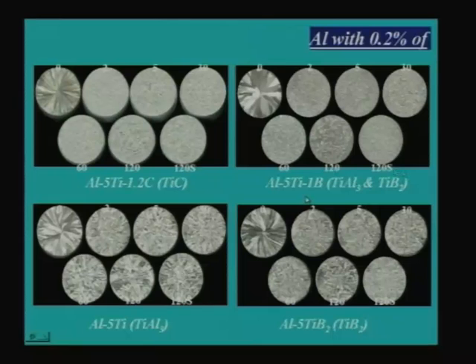and compared with different types of grain refiners. One is an aluminum 5 titanium grain refiner. Aluminum 5 titanium grain refiner has only TiAl3 particles. So, here you have only TiAl3 particles acting as nucleating sites. You can see the grain refinement is not very good. Okay. This is without any grain refinement, you get a columnar grain structure which is typical of any casting, and if you add the grain refiner, you get some grain refinement but not very good grain refinement.